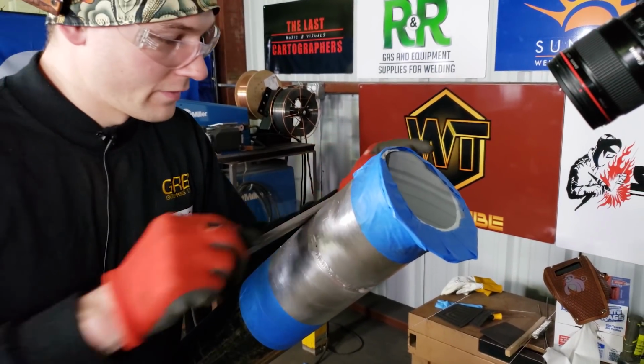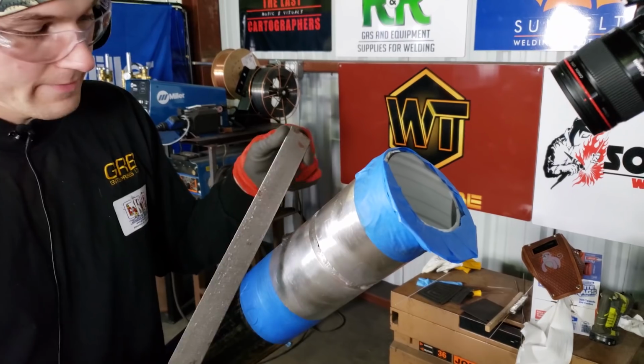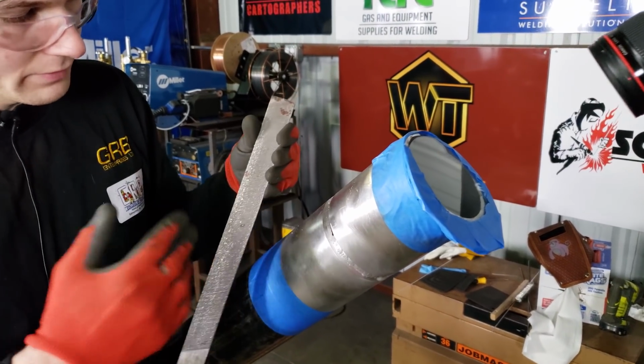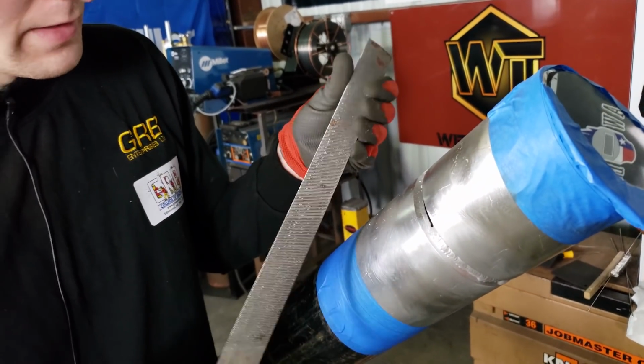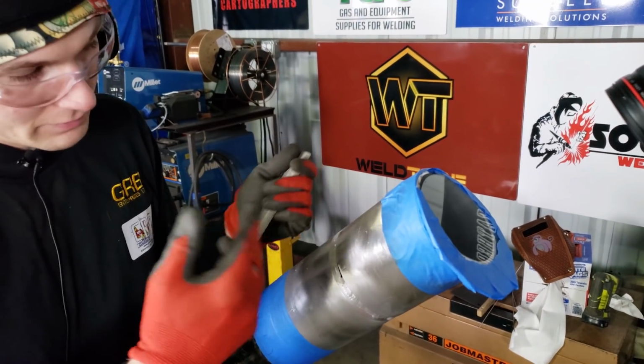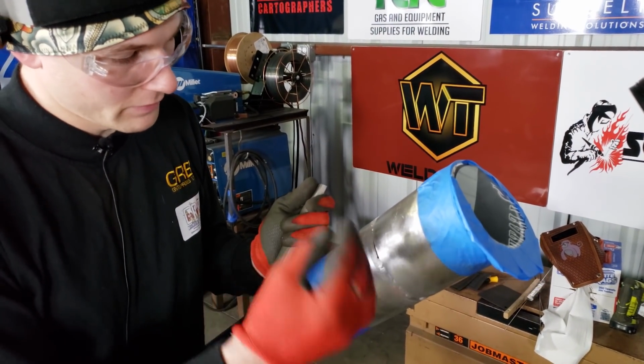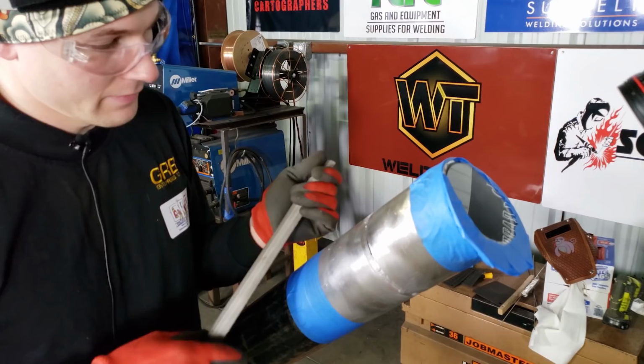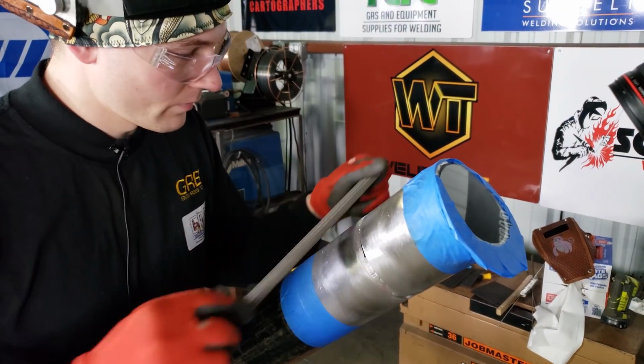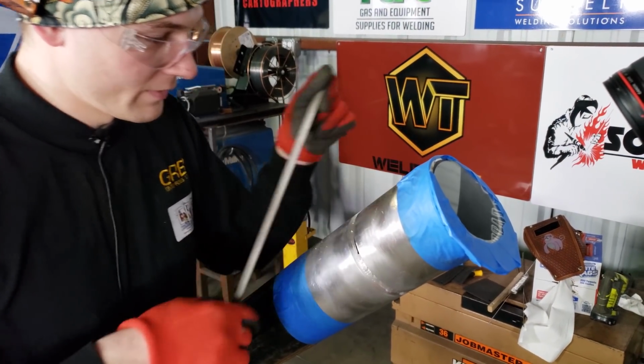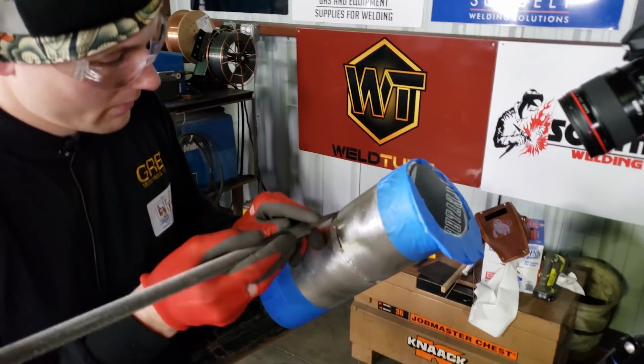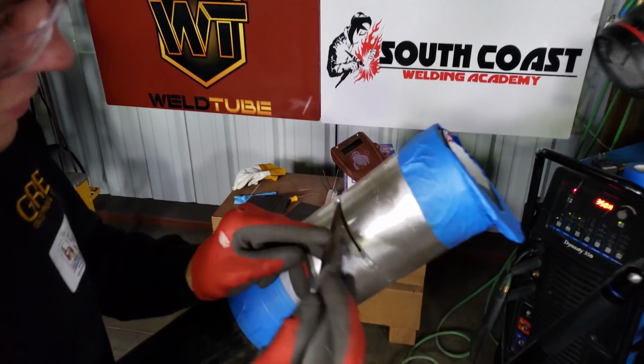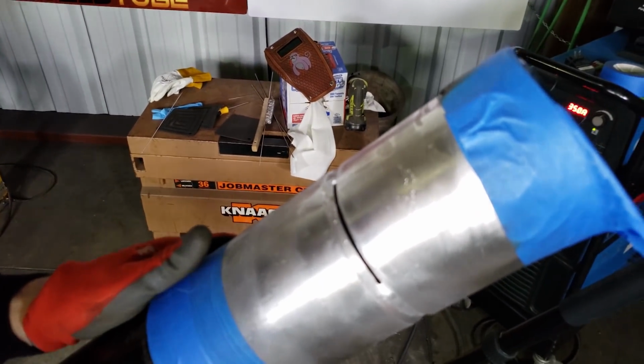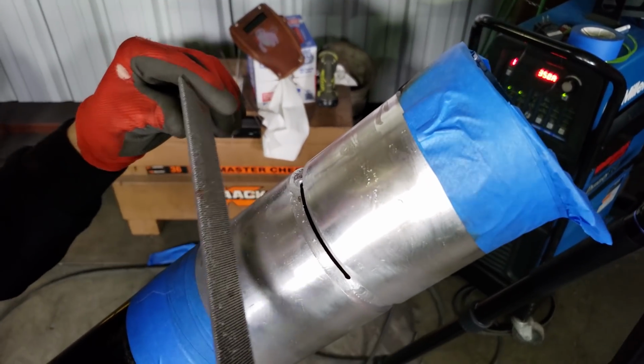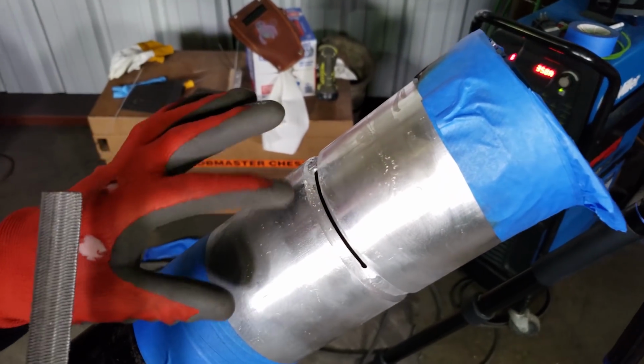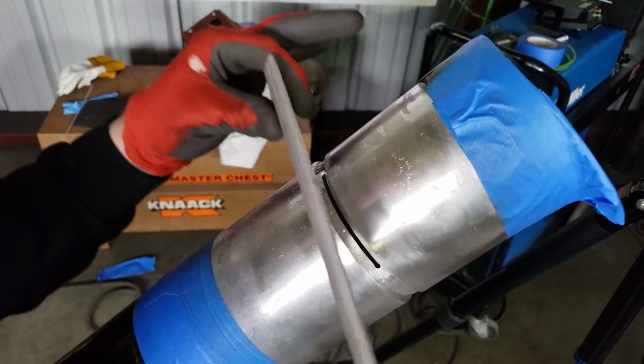Essentially what I'm doing here is removing the tack with the file, and as you can see, even with slow movement, it does contaminate the file. Going in this direction, it also has aluminum particles that fall into the pipe, which you really don't want. Once the tack is gone, you want a new file. Then I can pry the tack out, and there are oxides underneath the tack, so those I've got to clean.